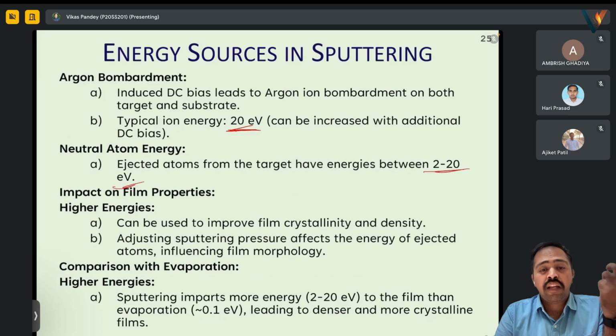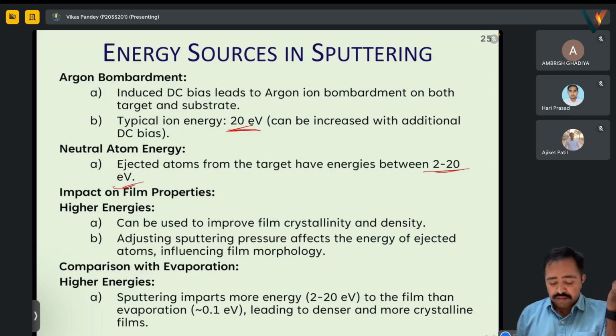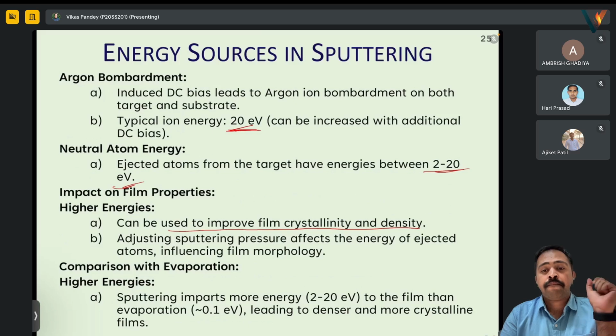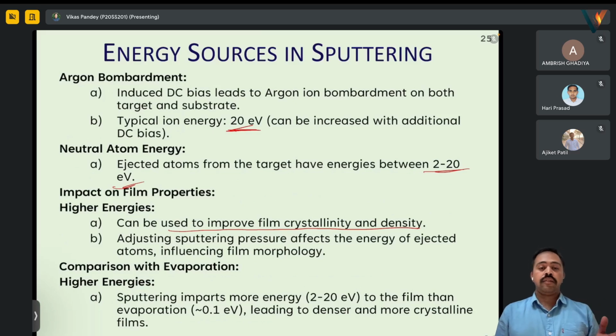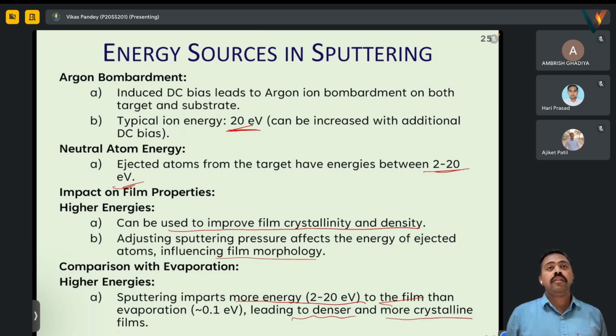If we are going for very high energy ions, then it can be used to improve film crystallinity and density. So sputtering pressure, at what pressure? These will have more energy based on the partial pressure or the gaseous pressure of the argon, and that will have an effect on the energy of the ejected atoms and will also influence the film morphology. If we compare it with evaporation, this has more energy, and that is why it will certainly have more surface defects compared to thermal evaporation, but it will create more dense and more crystalline films.